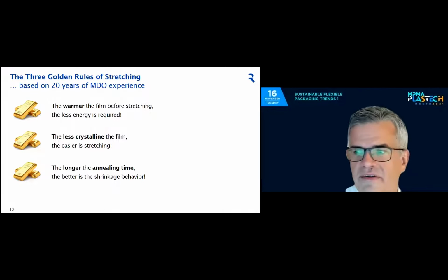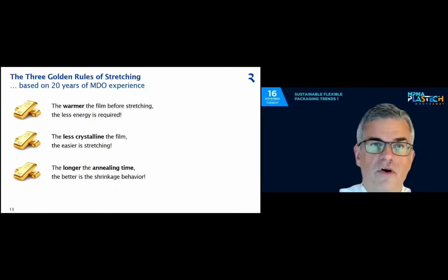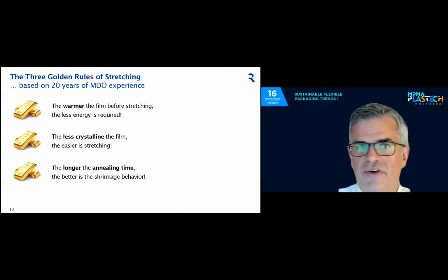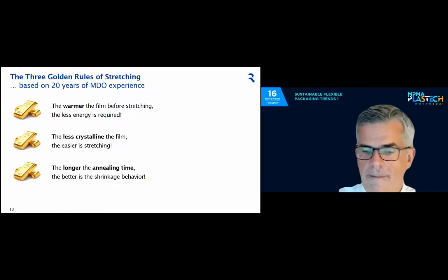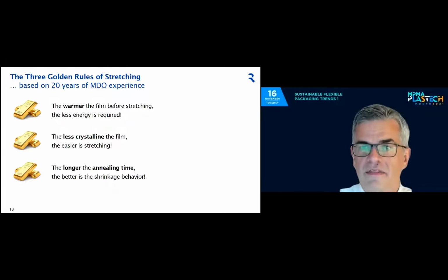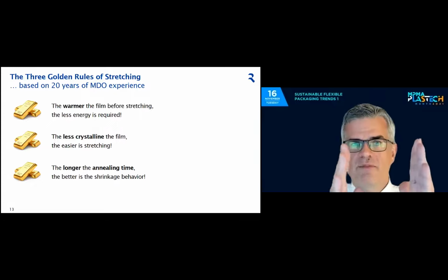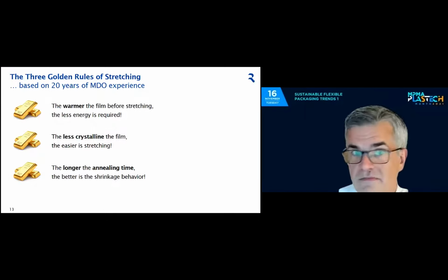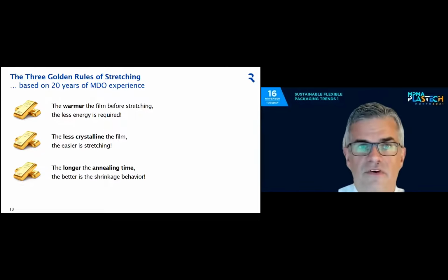How come? Well, a simple example. When we used the offline MDO in the past, it was an easy thing to do stretching if I do the production of the blown film on the first day and immediately do the stretching. If I have a certain period of time between producing the film and doing the stretching, then the process window on the MDO became smaller and smaller. So this is the reason why the inline MDO is more attractive than an offline MDO in terms of production stability of the process.